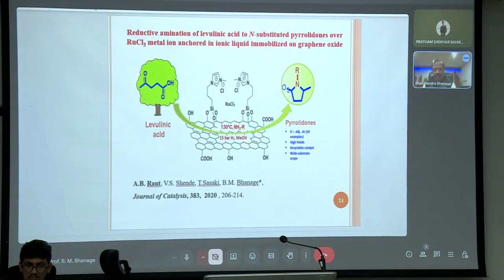Then we have taken another example in which levulinic acid is converted to pyrrolidones using reductive amination of levulinic acid. Here we need to take ruthenium metal anchored on an ionic liquid immobilized on a graphene oxide based catalyst. This catalyst is specially designed so that ruthenium is closely held between the ionic liquid groups which are anchored on the graphene oxide.